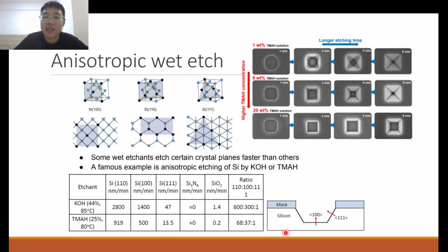And so what happens is that we tend to get these profiles, where your 111 plane that etches so slowly is still not completely etched. So there is this slanted profile, and we can see that it's somewhat like a pyramidal shape. So this base here, 100, is like this base here, and these 111 planes are like these slanted edges over here. So it's like a sunken bevel kind of profile.